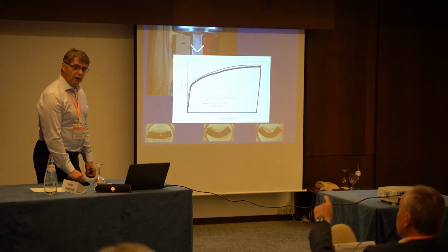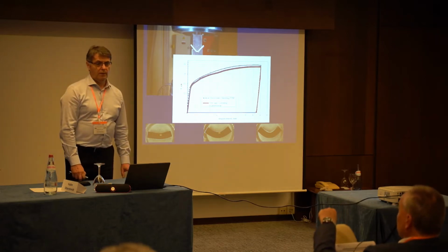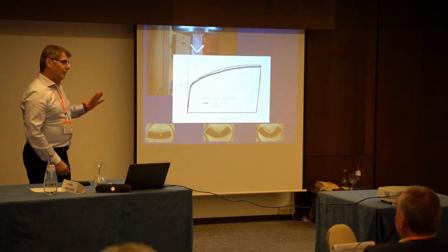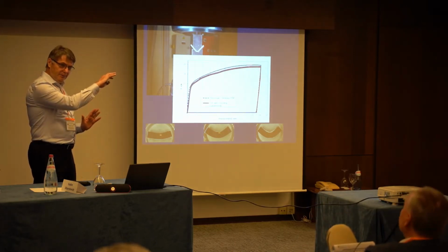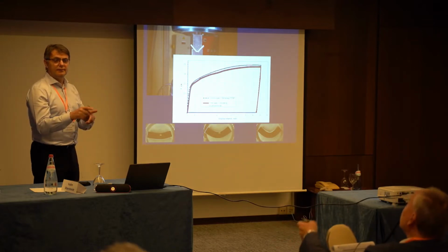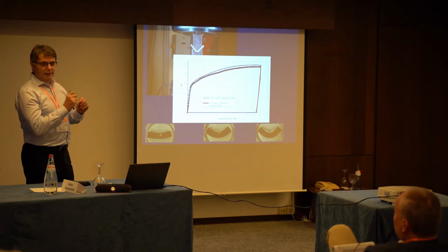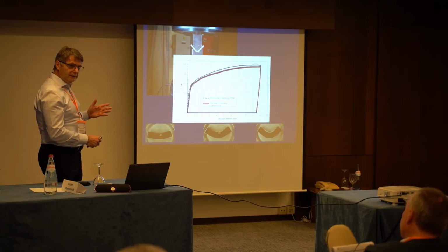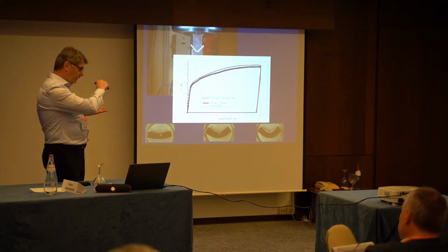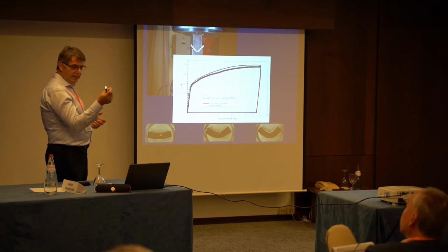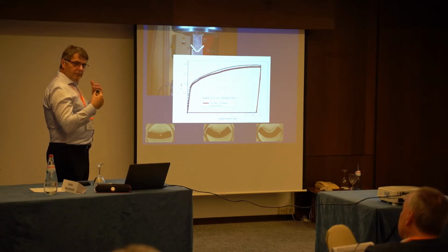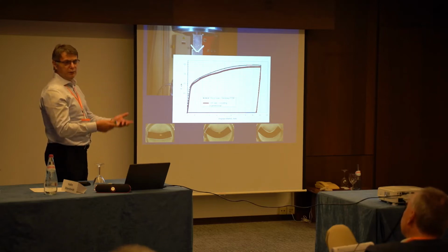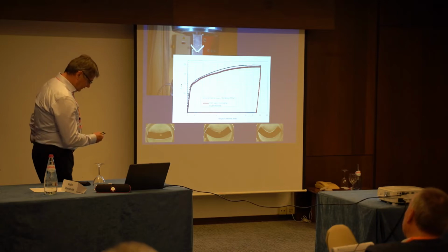Sorry, has your model already accounted for the martensite transformation, or not? So just with the original? This is the point. Okay. We actually use the true stress-strain curve. So you decoupled it, right? We don't play with the martensite. Just the tensile properties. But when you get this combined curve, in this curve you already have some martensite inside, but actually the computer doesn't know that you have martensite. You put just the values, and then with simulation you got this result here, of course.